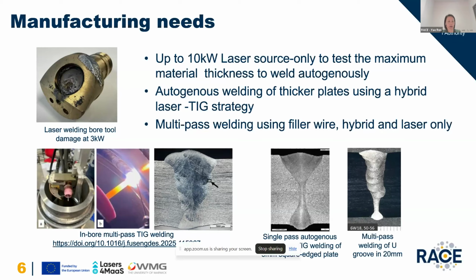the laser power, to identify how much laser power we need to penetrate a certain pipe wall thickness. We did some trials at other suppliers' sites, and we found out 10 kilowatts also struggles to penetrate about 10 millimeter using a multi-mode laser. If we wanted, we could use a combined hybrid solution, which means we use laser and TIG together to introduce more heat and produce a multi-pass solution, which could make the joint up to 10 or even 20 millimeter.